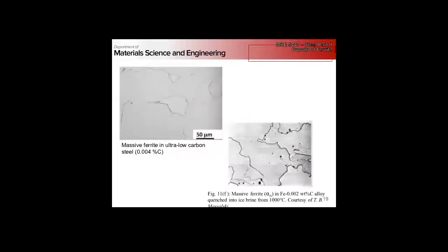So we have microstructures that look like this. Nice, not perfectly clean equiaxed, right? But notice the carbon contents of these. These are ultra low carbon steels. This is weight percent carbon, so 4/1000 of a percent, 2/1000, by weight.